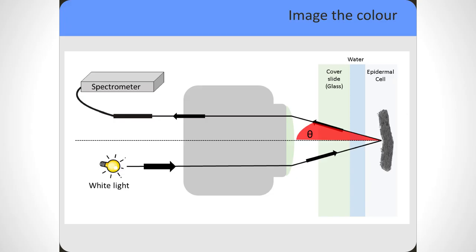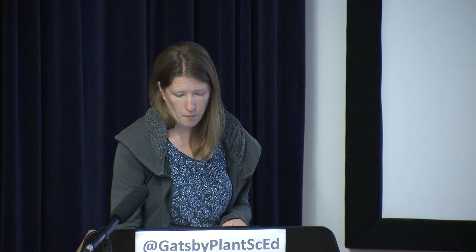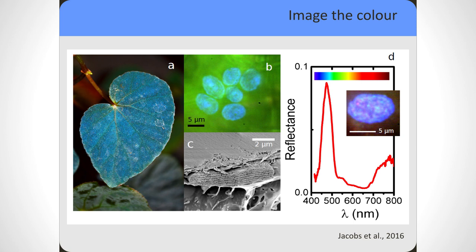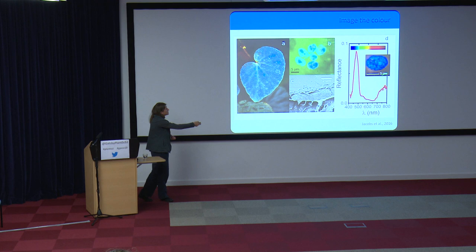You can do this by collaborating with physicists who set up a spectrometer linked to a microscope, connected to a goniometer, which means you can measure not just the colour but the colour from multiple different angles. This is important because it's one of the defining features of iridescence — the colour changes from different angles. To confirm something is structural or iridescent rather than pigment, you need to measure colour from multiple angles. You can image the iridoplasts under a standard light microscope and measure that using a spectrometer to see the blue colouration, which has a very sharp and defined peak of high reflectance.